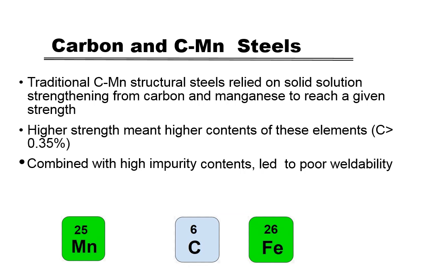Traditional carbon manganese structural steels relied on solid solution strengthening from carbon and manganese to reach a given strength. Higher strength meant higher contents of these elements, generally carbon above 0.35%. Combined with high impurity contents, it led to poor weldability. So if you're getting your carbon content up there and then you have things like phosphorus and sulfur and other impurities, it's going to lead to poor weldability.